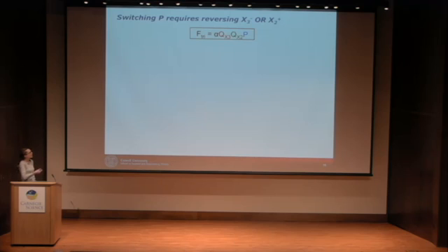So this trilinear term in the free energy has important implications for switching. Namely, if we want to switch P, so take P to minus P, we need to reverse the sense of one but not both of the octahedral rotations. So that means if we have a rotation that's initially going clockwise, it will then be going counterclockwise after the switching. So say this is our initial state. We have this polarization, and these are what these two octahedral rotation order parameters look like.